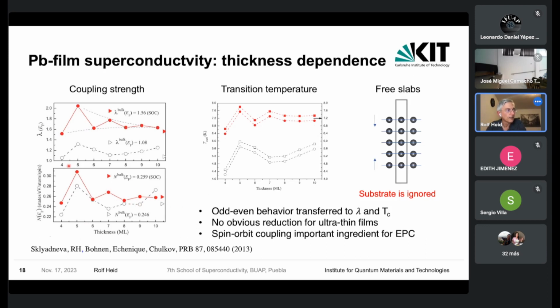So we have been looking at slabs from 4 to 10 monolayers thick. For 10 monolayers, already the calculations become quite demanding. But we can see that the coupling constant now for the monolayer shows indeed this kind of oscillatory behavior, and it mimics the behavior of the density of states, which is due to the presence of these quantum well states. However, this variation is actually enhanced, so this is not the only explanation. You can nicely see here this variation, but also the strength of the coupling matrix elements follows a similar variation.